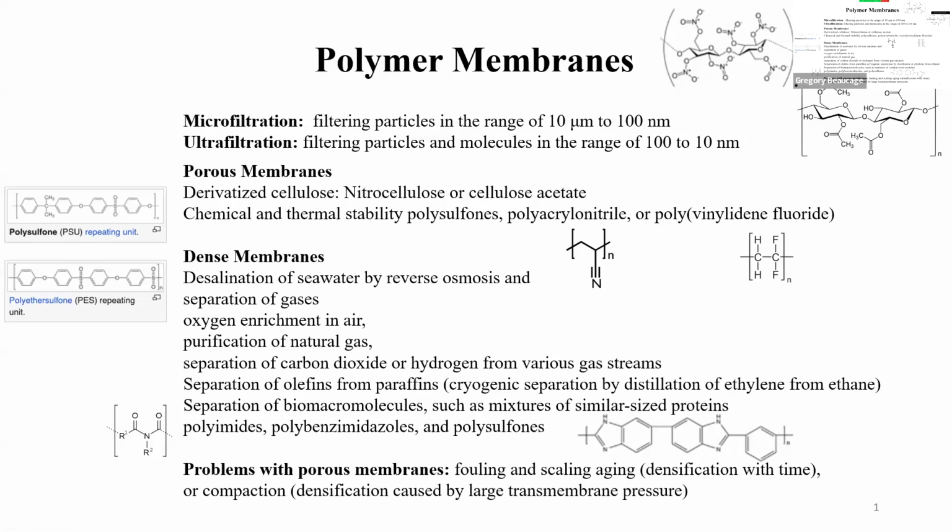The permeability of the membrane is going to be a combination of the solubility and the diffusion coefficient, multiplied. The diffusion coefficient times the solubility gives the permeability. So you need the two things together.